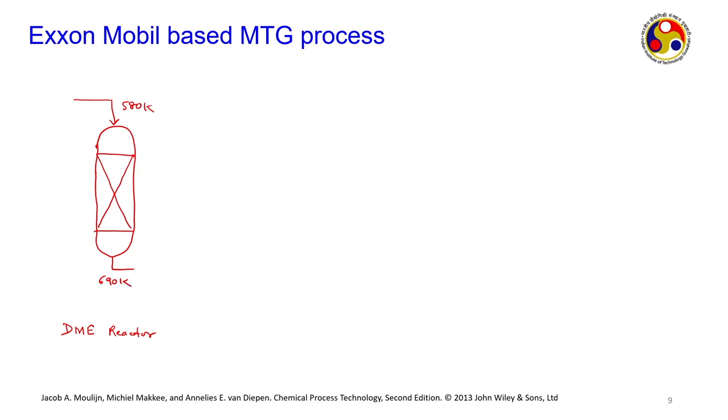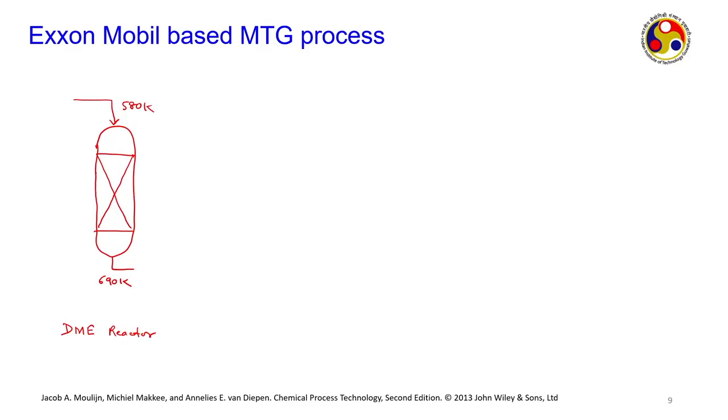Okay, so now you have one stream. At this stream, let me draw the gasoline synthesis reactor. Then I'll complete the loop. So what they do is they use a series of these gasoline synthesis adiabatic reactors. So when you use a series of these reactors, there is the catalyst, it may deactivate. In fact, the deactivation rate is pretty high, within months it deactivates. Deactivates implies coke deposition is there. What you do, you then send oxygen, you combust it, take away as CO2 and again reuse. So if you have a series of reactors, once one of the reactors gets deactivated, you take that out, meaning you disconnect it from the loop and carry out the reactions in the other reactors. So that's why it uses a series of reactors.